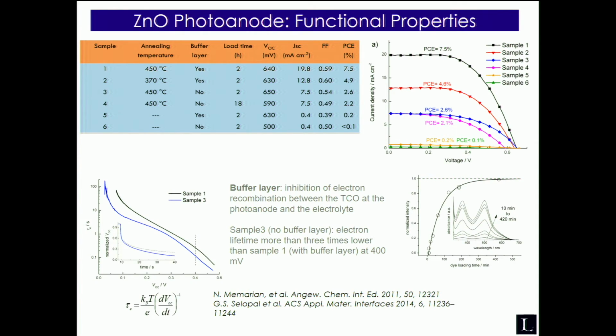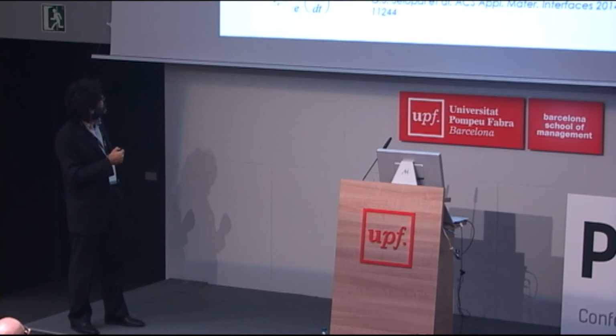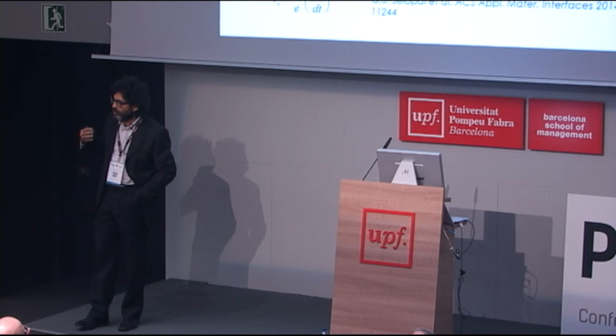We were also very happy to clearly identify the effect of the buffer layer. You can see here without buffer layer and with buffer layer, this is the electron lifetime in our system, which is significantly increased due to the inhibition of the back reaction from the conducting glass to the photoanode.